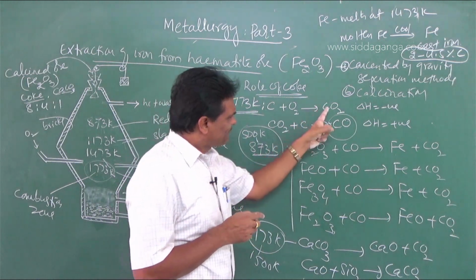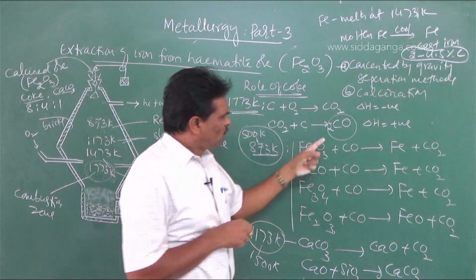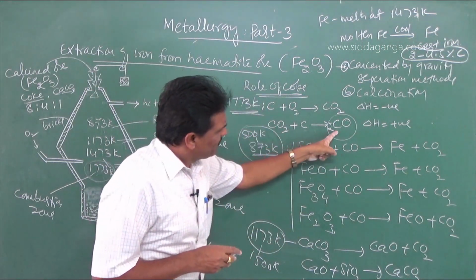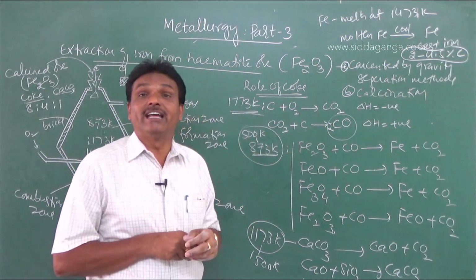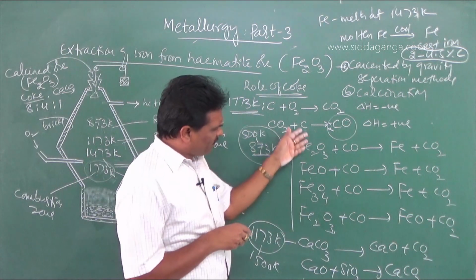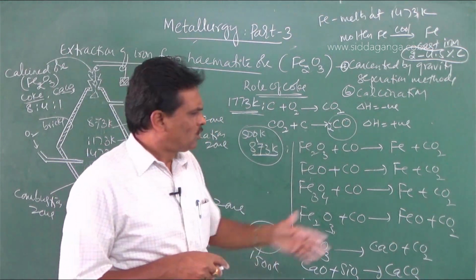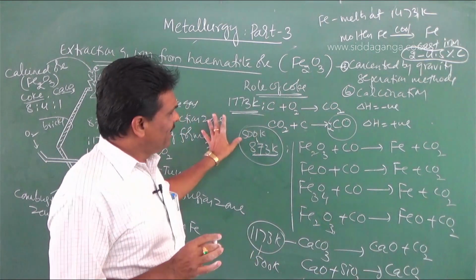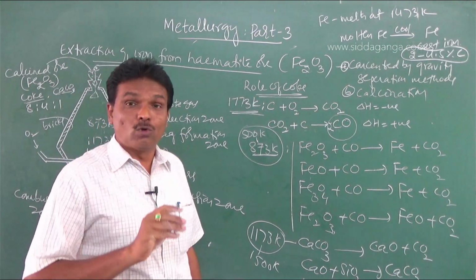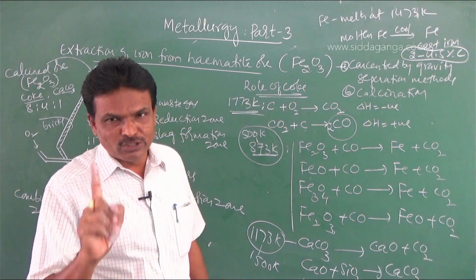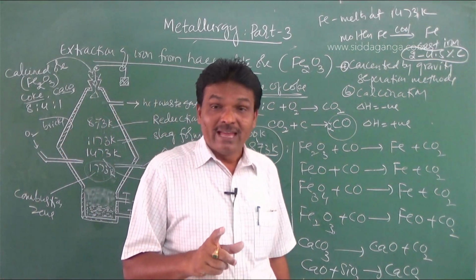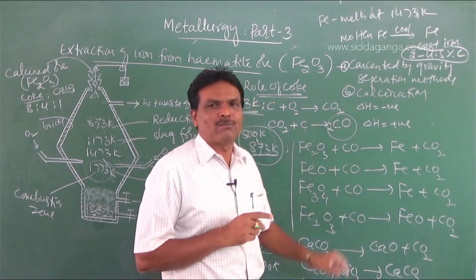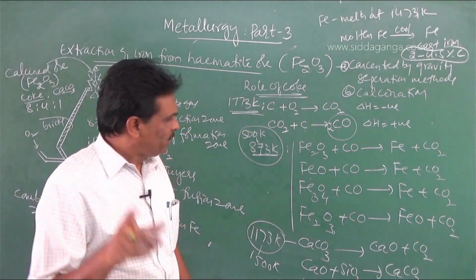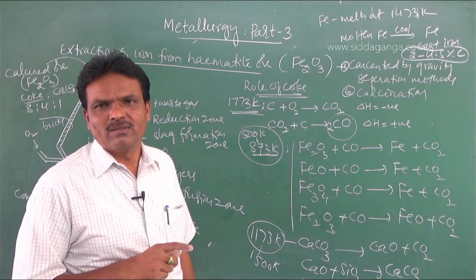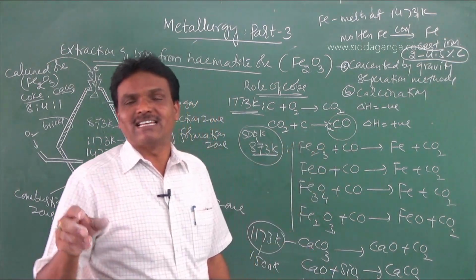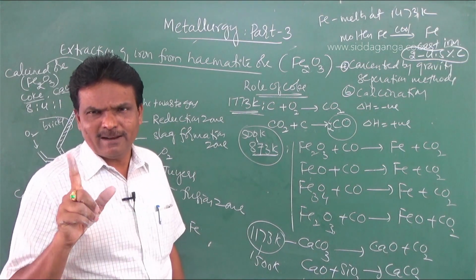And also this carbon dioxide is reduced by coke to form carbon monoxide, which means that coke produces a reducing atmosphere of carbon monoxide that is required for the reduction of oxides of iron. ನೋಡಿ ಎಲ್ಲ ಆಕ್ಸೈಡ್ ಆಫ್ ಐರನ್, they are all reduced by carbon monoxide to form iron. ಅಂದ್ರೆ ಒಂದು ಸ್ಪಷ್ಟ ಮಾಡ್ಕೊಳ್ಳಿ, ಇಲ್ಲಿ ಕೋಕ್ ರೆಡ್ಯೂಸಿಂಗ್ ಏಜೆಂಟ್ ಅಲ್ಲ. The role of coke in the metallurgy of iron is, it is not a reducing agent, it acts as a fuel and it produces a reducing atmosphere of carbon monoxide. This carbon monoxide reduces metal oxides to metals. ಈ ಕಾರ್ಬನ್ ಮೊನಾಕ್ಸೈಡ್ ಮೆಟಲ್ ಆಕ್ಸೈಡ್ಸ್ ಅನ್ನ ಮೆಟಲ್ಸ್ ಅನ್ನಾಗಿ ಕನ್ವರ್ಷನ್ ಮಾಡುತ್ತೆ. ಕ್ಲಿಯರ್? ಸೊ ವೆರಿ ಇಂಪಾರ್ಟೆಂಟ್ ಪಾಯಿಂಟ್.